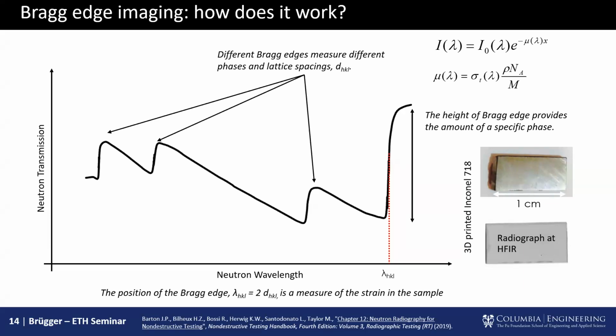So if we now carefully measure the transmitted signal, then that is again equivalent to, instead of having peaks, now we have troughs or Bragg edges. And those Bragg edges, again, are indicative of lattice spacing and phase fraction. So depending on their magnitude and their position, we can get the same information. It's more difficult, but ultimately it's the same method, just in transmission.